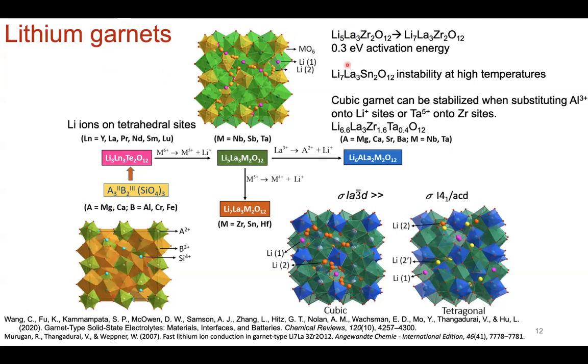So the increase in lithium concentration going from lithium-5 to lithium-7 will actually bring down the activation energy to like 0.3 eV for lithium ion migration, which is relatively low, actually. And so, in replacing and substituting in some of the tantalum with zirconium, you can also see improvements in the ionic conductivity.